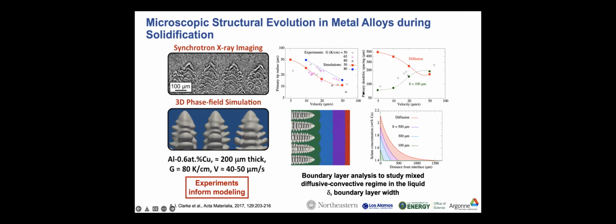That said, if we look at primary dendrite spacing versus velocity, open points are experiments, our first simulations actually show completely the wrong trend. So why is that? When we do directional solidification, we basically start snow plowing solute in front of the advancing solid-liquid interface, and this creates a solutal boundary layer that we establish. And you can imagine that if we have real effects like convection in the melt, this can actually sweep away solute and affect the buildup of that solutal boundary layer.